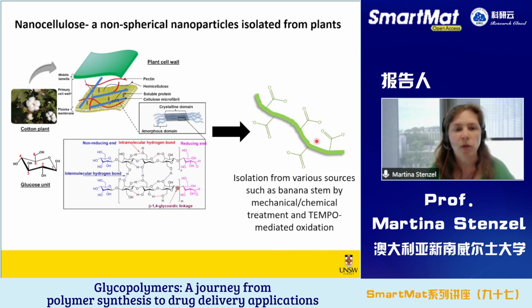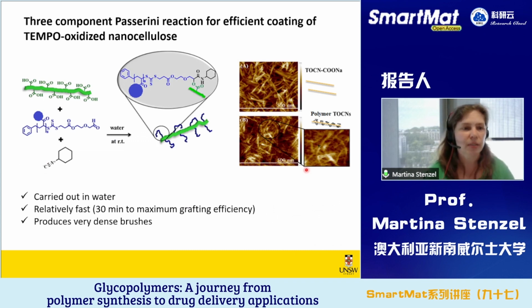And so what we did is we used nanocellulose. Nanocellulose is obtained from plants, and nanocellulose are long elongated polysaccharides bound together by a crystalline domain. Depending on the source, it can be around 500 nanometer in length, but it's only a few nanometer in diameter, so very, very high aspect ratio. When you isolate nanocellulose by TEMPO-mediated oxidation, you get particles that have a lot of carboxyl groups on the surface. And these carboxyl groups can now be readily functionalized with polymers.